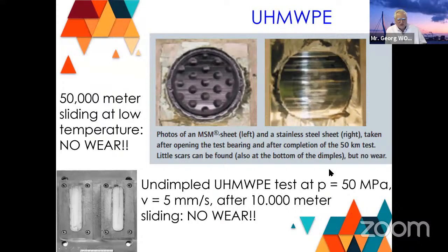So with this material, there was a 50,000 meter test, and this test was running for an incredibly long time at a temperature pattern where the temperature changed from -30 to +45 degrees. And when you look at this material after this incredible test, you see it has no wear. It just has some marks, some scars from the movement, but it's still like new, and you could make another 50,000 meters, but that would be too costly. The test was running at the University of Stuttgart, and it was very expensive.